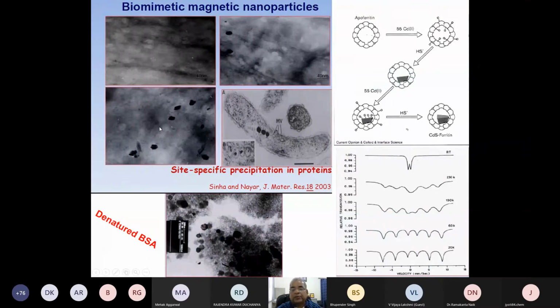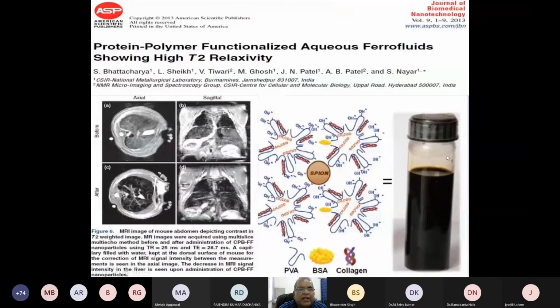And again, we know that protein is a very sensitive structure. If we heat it a little bit or stir it a little bit during the solution formation, it will denature. So intentionally, we denatured the protein and then again carried out the in situ nucleation and the growth of magnetite particles. We found that the protein has lost its control over shape, size, and the agglomeration of the magnetic nanoparticles. You can see in the bottom microstructure here. So it's very important not to allow the protein to denature when you are carrying out your material synthesis. Then we confirmed, we did some physics out of it. We found that our magnetic nanoparticles that we synthesized in the native protein structure were superparamagnetic in nature and can be used for different biomedical applications.